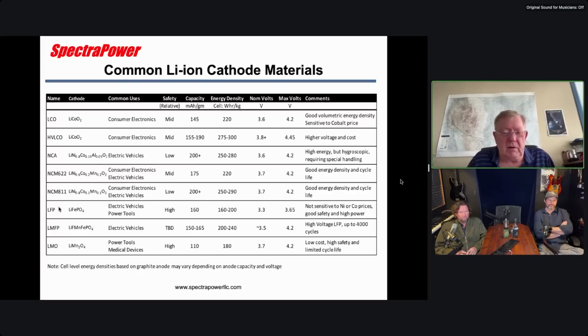Then there's iron phosphate, which you use a lot in power tools, and in China they use them in EVs quite a bit. It has much lower energy density than these others, but it has some advantages. So there's no nickel or cobalt, which are materials that are expensive and potentially rare. It's iron phosphate. So F is for Fe, iron, and P is for phosphorus. And so it doesn't use exotic materials, and it's not sensitive to nickel cobalt pricing. Because it's lower energy, it tends to be safer, and the way they design with it is for high power, and that's why you see it in power tools.